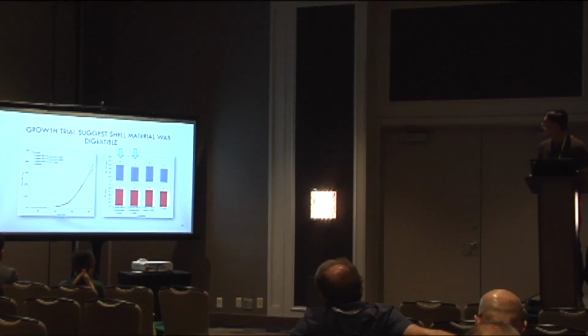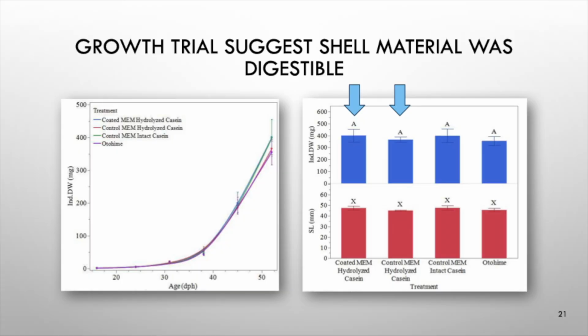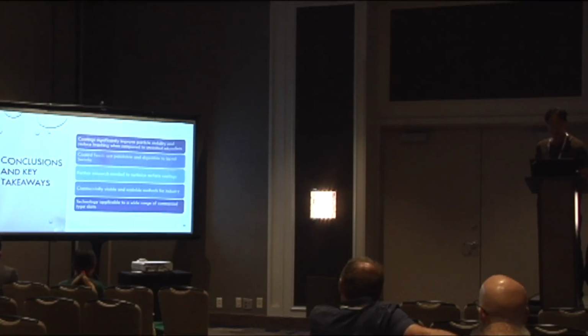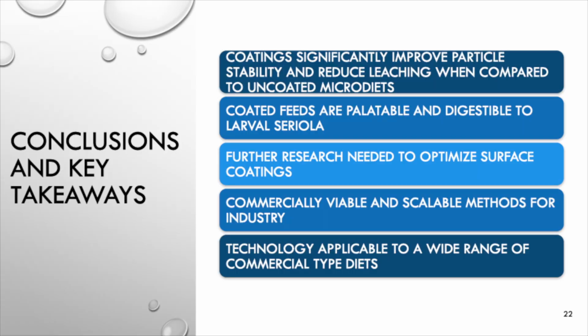And on the right, you can see individual dry weight and standard length for each treatment at the final time point of the study, and you can see that the coated MEM also did slightly better than the uncoated hydrolyzed MEM. So overall, for my research thus far, we concluded that the coatings significantly improve particle stability and reduce nutrient leaching when compared to uncoated microdiets.